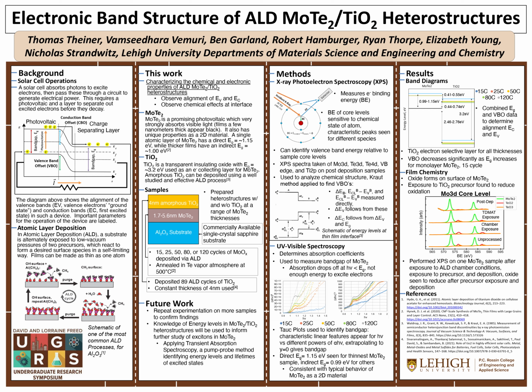So on the film chemistry side of things, the most interesting thing we saw is that you do have a slight reduction in the amount of oxide you see on these samples after you expose them to the precursor that we use to deposit titania. This isn't terribly surprising. These precursors are, by definition, reducing agents. They exist to be oxidized, but it is interesting to document.